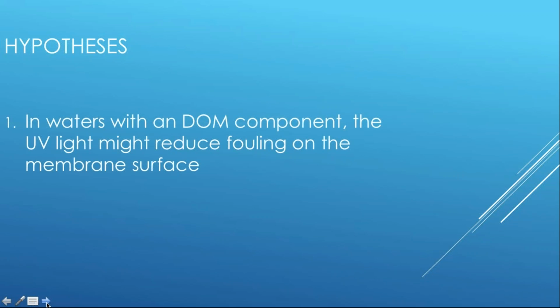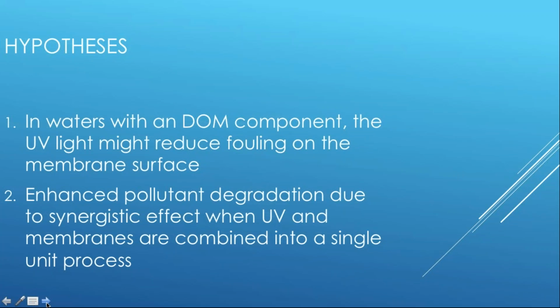One of our hypotheses was, if we have a large DOM component in the water, we might be able to reduce fouling on the surface of the membrane, because we've got this possible photocatalytic oxidation that could occur because these membranes are composed of titanium dioxide and exposed to UV light. Secondly, we thought, hey, not only could we reduce maybe DOM, but we also might see an improved effect on pollutant degradation, such as micropollutants. Whereas we wouldn't see these effects if we just treated, typically, by removing pollutants through membrane filtration, and then possibly how typical water treatment utilizes UV for photolytic degradation.